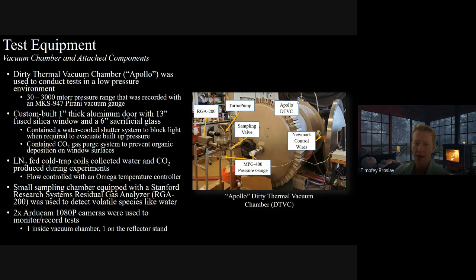The vacuum chamber housed a variety of equipment as well. The dirty thermal vacuum chamber, which we called the Apollo, was used in the pressure range of around 30 to 3,000 millitorr to conduct these optical mining tests. Instead of using the door that came with this chamber, we had to build a custom 1-inch thick aluminum door with a 13-inch fused silica window and a 6-inch sacrificial glass to allow the light from the reflector and bulb to shine through. It also contained a water-cooled shutter to block light when we needed to evacuate built-up pressure. It also had a carbon dioxide purge gas system to prevent organic deposition on the window surfaces. I'll explain that in a little bit.